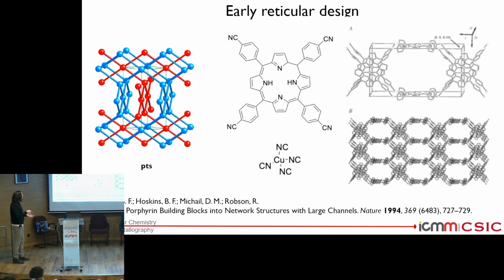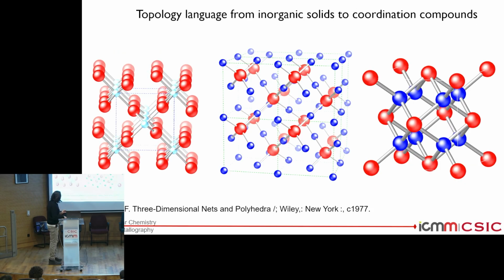Okay, so other examples, for example, here showing how instead of tetrahedral, you can also connect square-shaped ligands. And if you have this type of square-shaped ligand with, again, tetrahedral, you will have the same network that you have in other inorganic compounds like platinum sulfide. In platinum sulfide, called PtS, you have sulfur and platinum atoms with the same square and tetrahedral coordination environment. So that was published already in the 90s. And here, notice that in this paper in Nature they mentioned a network with large channels. But here we are talking only about channels, not porosity yet. I will get to that in a minute.